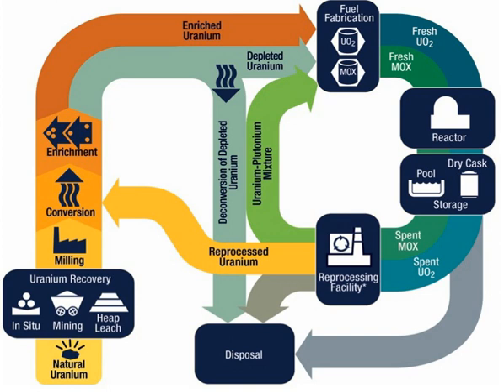Usually milled uranium oxide (U-308, triuranium octoxide) is then processed into either of two substances depending on the intended use. For use in most reactors, U-308 is usually converted to uranium hexafluoride (UF-6), the input stock for most commercial uranium enrichment facilities. A solid at room temperature, uranium hexafluoride becomes gaseous at 57 degrees Celsius. At this stage the conversion product still has the natural isotopic mix: 99.28% U-238 plus 0.71% U-235. For reactors such as CANDU which do not require enriched fuel, the U-308 may instead be converted to uranium dioxide, which can be included in ceramic fuel elements. In the current nuclear industry, the volume converted directly to UO2 is typically quite small compared to that converted to UF-6.